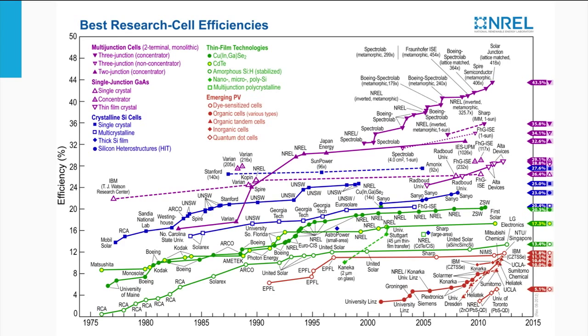The purple colored markers represent the 3-5 technology based on single, double and triple junctions and have efficiencies ranging from 26% up to 44% under concentrated light conditions. The blue lines and dots represent crystalline silicon technology based on monocrystalline and multicrystalline silicon. The record efficiency ranges from 20 up to 25% under standard 1 sun illumination conditions, and 27% can be achieved under 92 suns illumination.